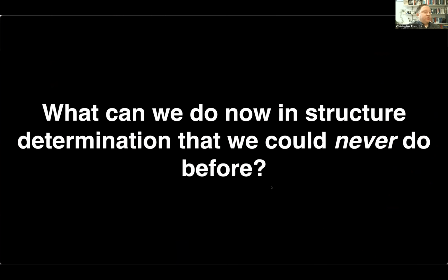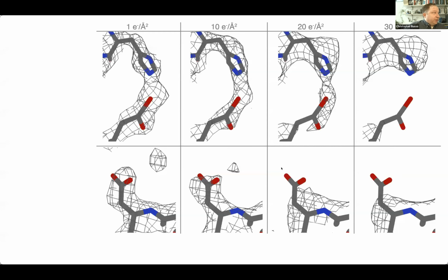Right, so in terms of structure determination, what can we do now that we could never do before? Well, the first thing that we can do is actually use the first electron per angstrom squared. So this is just showing an atomic model of a couple of side chains here, and the corresponding map reconstructed from each frame all the way out to 30 electrons per angstrom squared. And you can see here by 20 or 30, the side chains are completely destroyed. But as you come back up here, the water molecule shows up and all the density for the side chain comes back. And now the first electron per angstrom squared really is the best map. This is the best one, and you want this one.